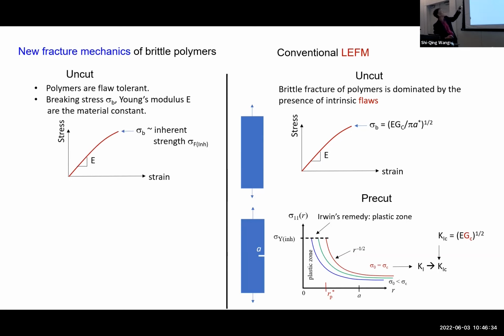For polymers, our conclusion is pretty clear. When you have no cut, the strength is merely, roughly speaking, revealing the inherent strength. Fracture mechanics is not in the business, per se. At 50 microns, 100 microns, you just need your sample to be clean, not to have flaws of a millimeter, which we don't.